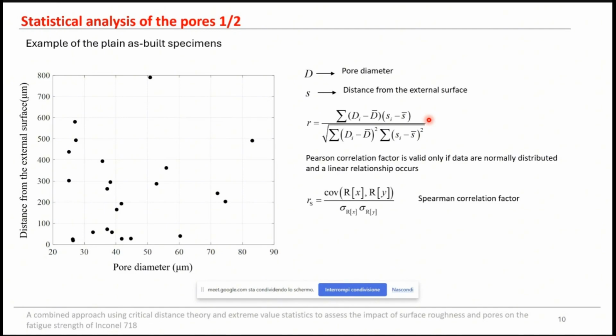Thus, we moved to the use of the Spearman correlation factor and Kendall correlation factor. But in all cases, we obtained low correlation factors, much lower than 0.5. This rigorously does not mean that no relationship occurs between the variables, but given the low correlation factors obtained, we analyzed the two quantities separately.